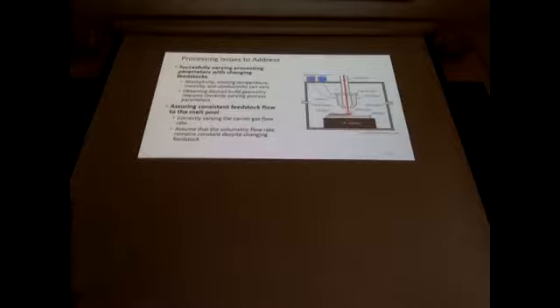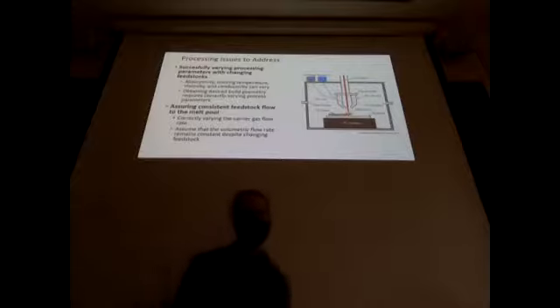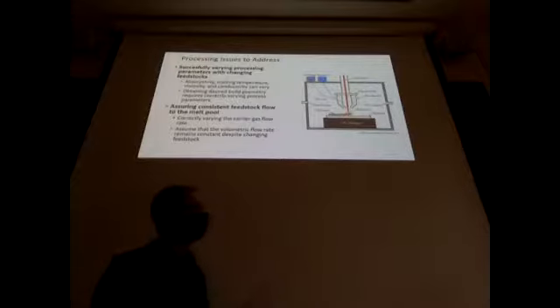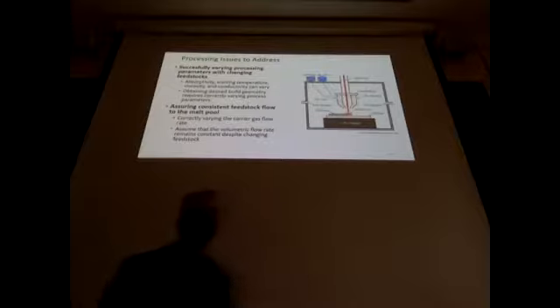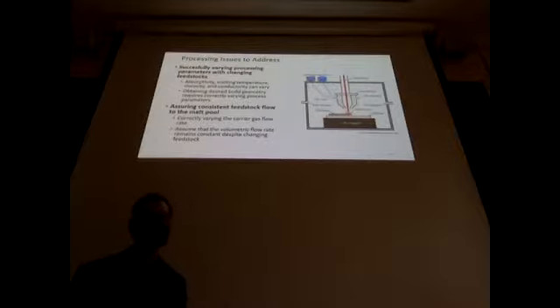So the issues that we wanted to address in this project, and this is a schematic of what we're dealing with, is directed energy deposition where you have two powders, and this is the easy case where we had aluminum and titanium that we are trying to put together and deposit. And so the main thing is, how do we successfully vary the process, as I mentioned, with the fact that these powders are going to change how they absorb the laser power. The melting temperature probably changes, the viscosity of this material changes, and conductivity can change. So all those things impact your final process of that material.